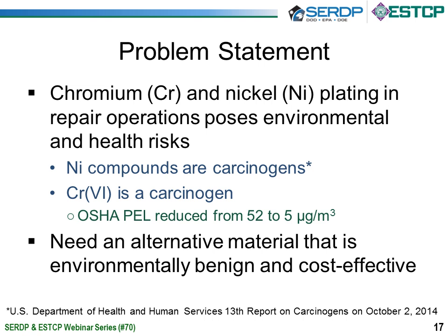So the main problem that we've been addressing in this project over the years has to do with the environmental and health risks associated with hexavalent chromium plating as well as nickel plating. Hexavalent chrome is a known carcinogen, and the OSHA PEL has recently been reduced from 52 to 5 micrograms per meter cubed. So that, combined with the inefficiency of the plating process and the mists involved with depositing chromium coatings, makes it more difficult to comply with all the regulations. So an advanced alternative that can compete both on a process and cost perspective is needed for these technologies.